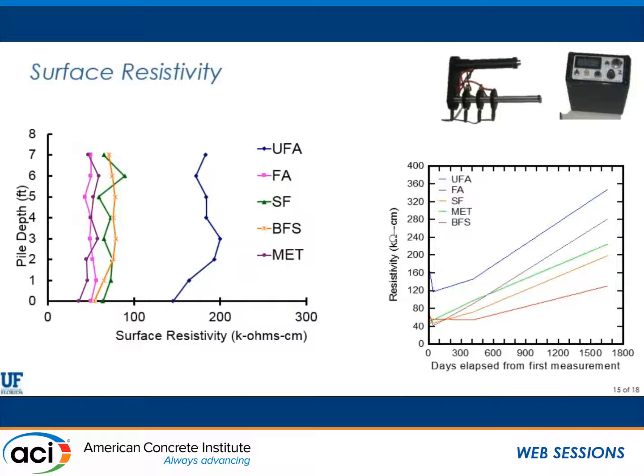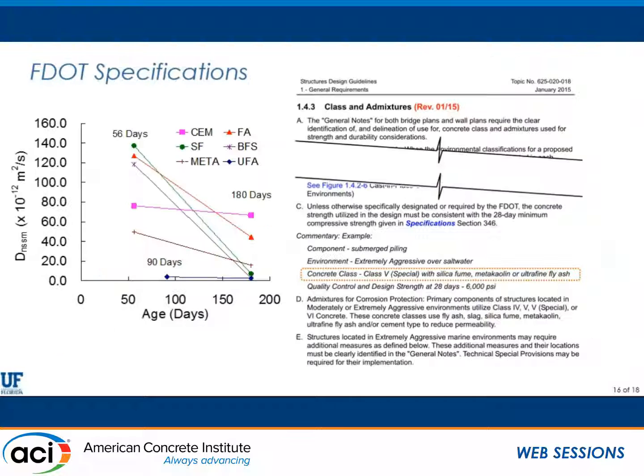The DOT is very interested in surface resistivity, so we did some field measurements with that, which is a really tough test to get consistent in the field because the moisture content of the concrete is extremely important. We did some testing, fairly consistent with the exception of the ultrafine fly ash. Not really sure why we got some elevated readings with that.